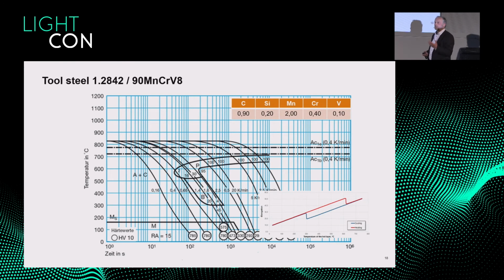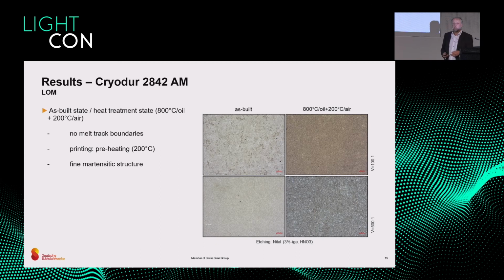The next one is the tool steel, and the design is simply developed by looking in the brochures and looking for a martensite start temperature. A lot of available machines have a preheating temperature up to 200 degrees. So we are looking for a material with a martensite start temperature below 200, and this is a cold work tool steel with a high amount of carbon. And so you never reach the phase transition. You stay in the austenitic regime, and this is a very easy to print material. You can use a preheating temperature of 200 degrees centigrade.